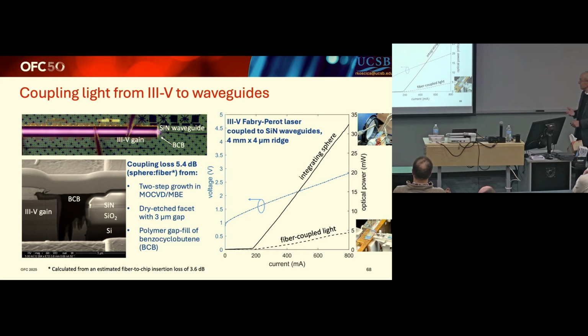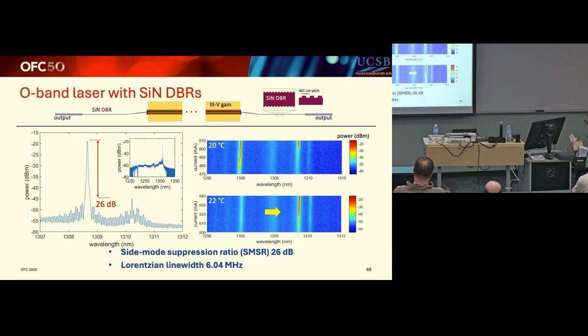So these are the latest results. See the reasonable LI curves. The fiber coupled light is lower, so again we're losing coupling here - it's not nearly as good as heterogeneous. Heterogeneous, as I said, is 0.1 dB. This is more like 3, 4, or 5 dB, but it's better than it was.